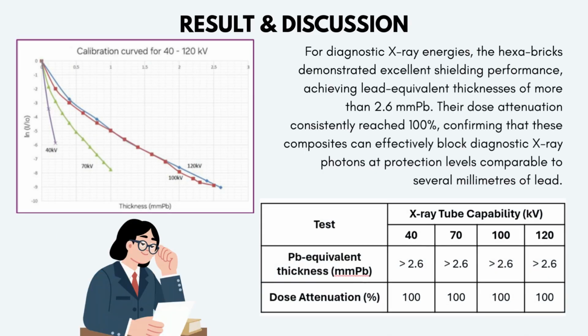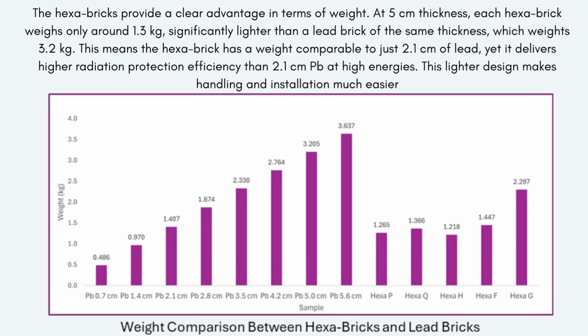For diagnostic X-ray energies, the hexabricks showed strong shielding, reaching over 2.6 lead equivalent thickness. They achieved 100% dose attenuation, confirming they can fully block diagnostic X-ray photons at protection levels comparable to several millimeters of lead. At 5 cm thick, the hexabrick is just 1.3 kg, less than half the weight of a lead brick. It matches the weight of 2.1 cm of lead, but outperforms it at high energies, making the shield both lighter and easier to handle.